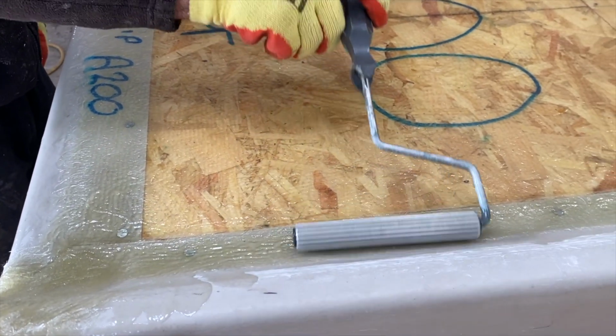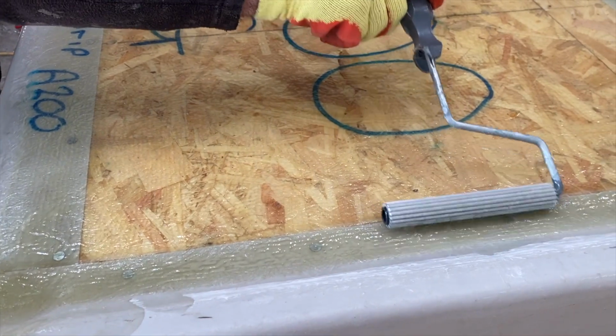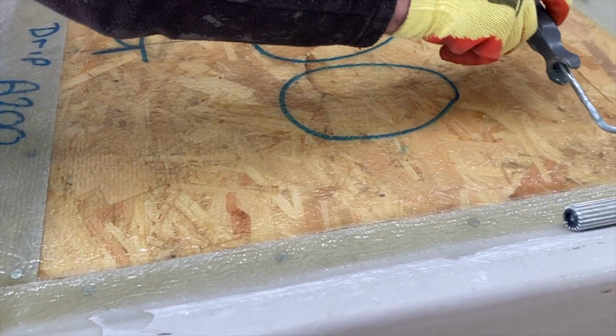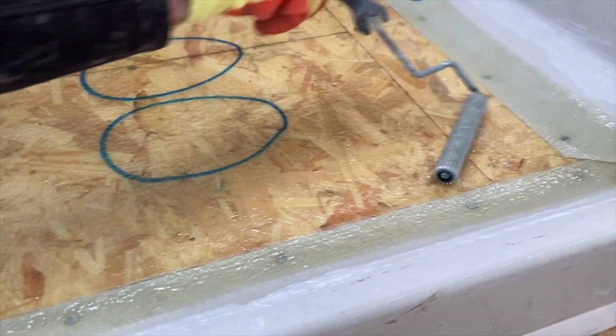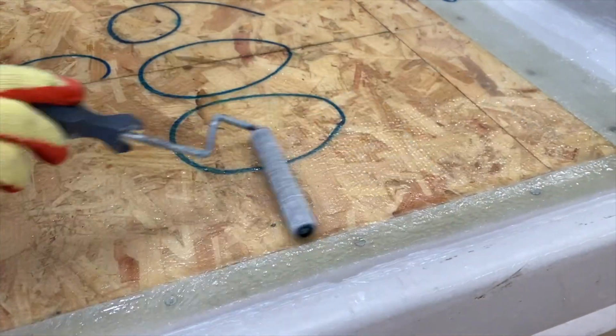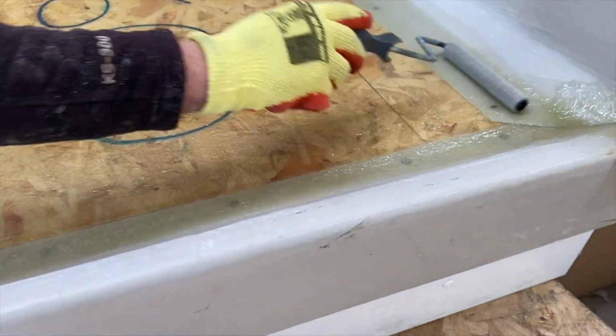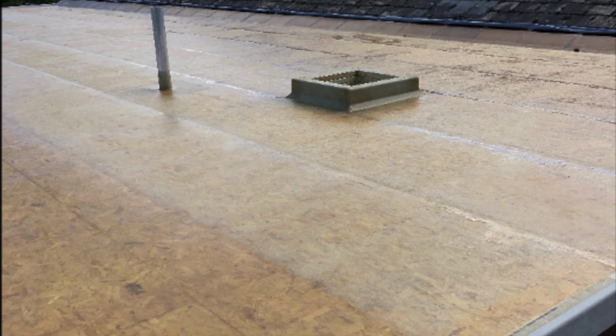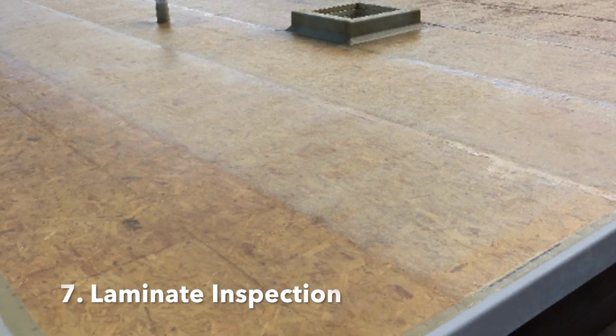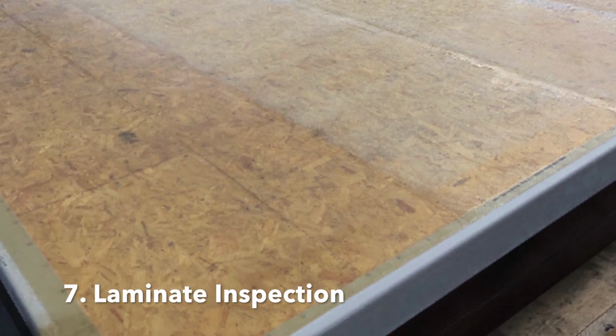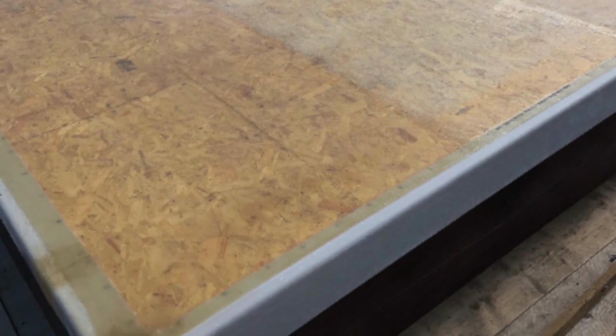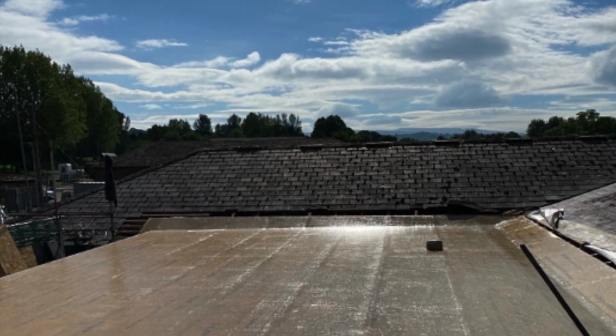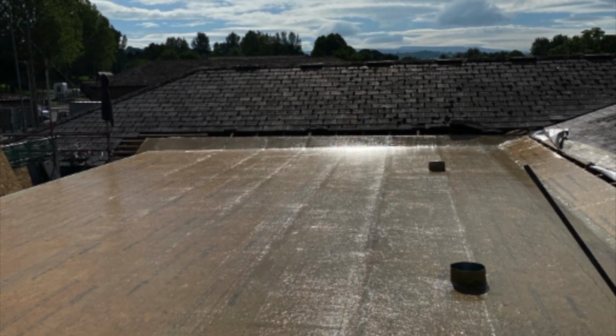Deviations from this, such as air bubbles or any poorly laminated areas, will lead to a premature lifetime of the fiberglass roof. Once complete, the laminate should look mildly glossy and completely seamless. You should allow it to cure for several hours or until it's mildly tacky.